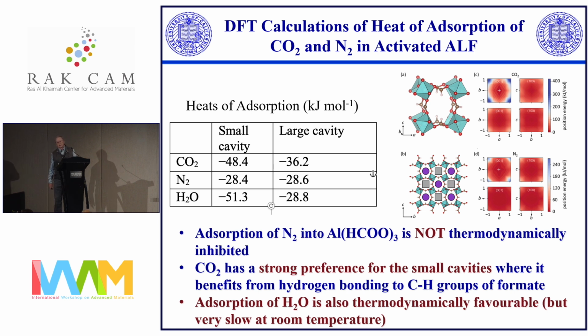So we've done DFT calculations with my colleague Piero Canepa and Jerry Deng in Singapore. And the interesting thing is, the small cavity absorbs the CO2 more effectively than the larger cavity, so we get different heats of absorption from the calculations. They agree overall rather nicely with our experiments. When you look at the nitrogen absorption, there's no reason why nitrogen wouldn't be absorbed. It's not as good as CO2. It's 28 kilojoules per mole or so. It's about the same in both cavities, but it doesn't go in.